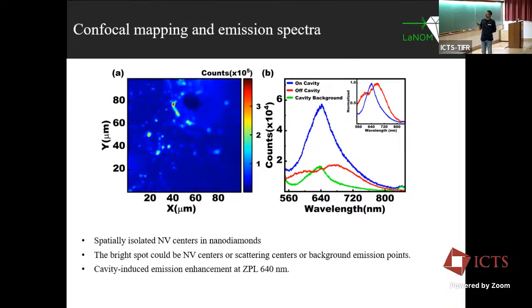So a PL spectrum alone may not be trustworthy. You have to do a lifetime measurement and see whether it is indeed a cavity-coupled NV center. And even if you get an NV, it can happen that it is not coupled to the cavity, because during fabrication you are not sure how the sample gets agglomerated. And when you make another film, it can give a lot of local stress and other things.